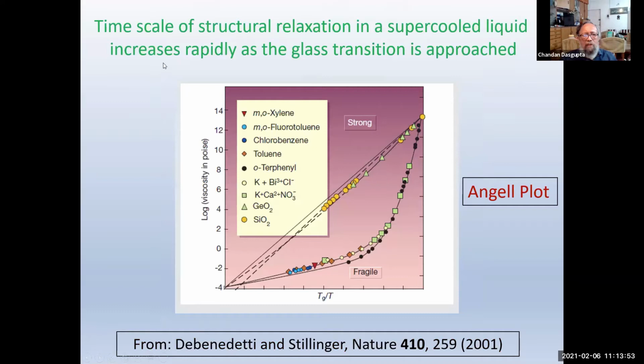The basic important feature of this approach to the glass transition is that the time scale of structural relaxation increases rapidly as one is approaching the glass transition, as one is reducing the temperature. And as you can see here, one is plotting the viscosity in poise on a log scale on the y-axis, and Tg over T, where Tg is a reference glass transition temperature.